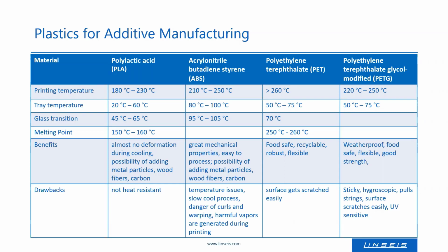The disadvantages of ABS are that there are some temperature issues, so it is really sensitive to the printing temperature and the temperature of the heated tray, so that temperature management is really crucial. And furthermore, the cooling process is rather slow. So by that one has the danger of cracks or splits in the layers, or one can have some curling and warping.